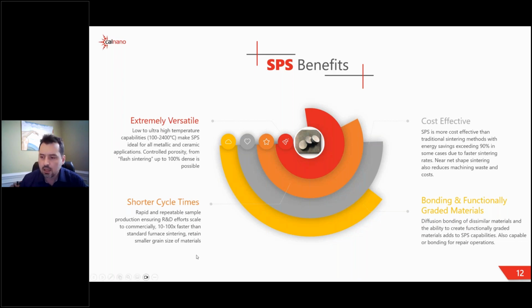So one of the benefits of SPS beyond that is because we are heating the material directly and we're not just heating up a giant box and waiting for that heat to soak in, we also get much faster cycle times. And so in the case of, say, HIPing, you might have to hold your material at 70 or 80% of the melting point for several hours, where we start off with about 45% of the melting point as a target for sintering at 5 to 10 minutes.